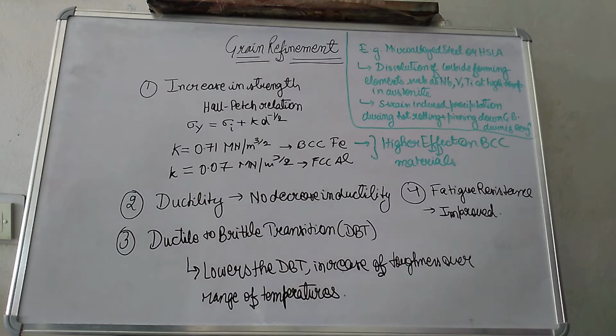The Hall-Petch relation has a K as the Hall-Petch constant, and this effect is more pronounced in BCC materials such as iron, which have a high Hall-Petch constant, rather than FCC materials such as aluminum, which have one order of magnitude less than the BCC material. The equivalent reduction in grain size will have one magnitude higher increase in strength in BCC materials like iron. So this is one of the important parameters, but this relation is applicable only in a certain size range, and below the micron size this relation does not hold applicable.